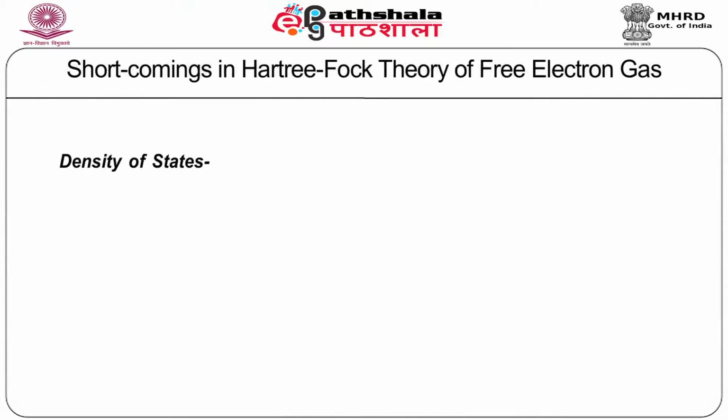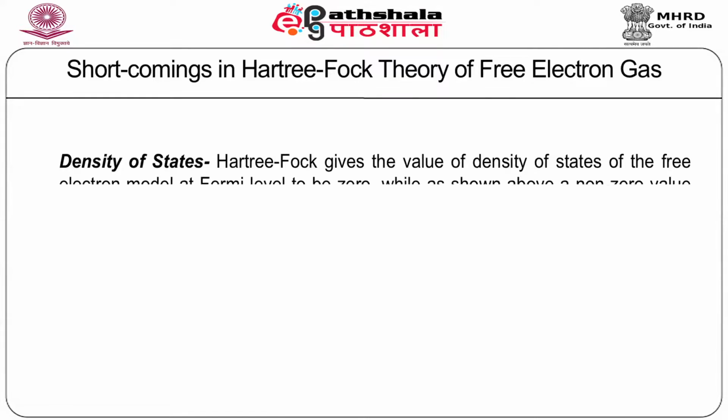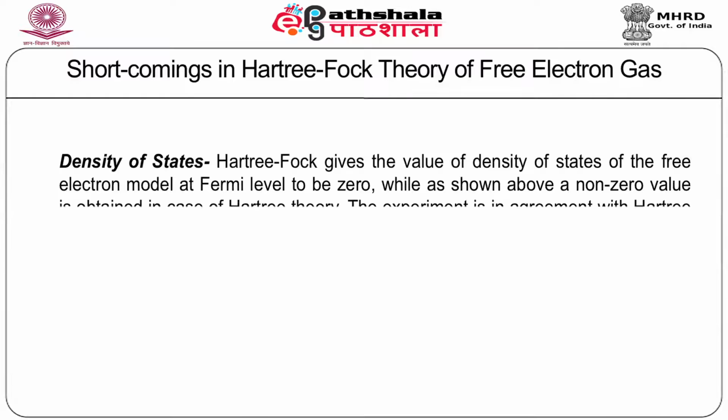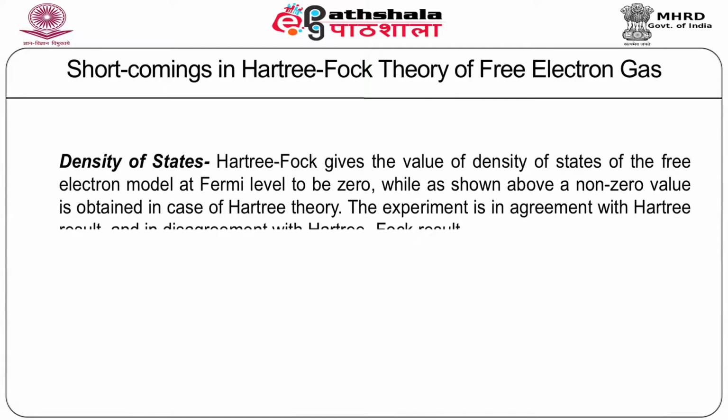The second issue is the density of states. Hartree-Fock gives the value of the density of states of the free electron model at the Fermi level to be 0, while as discussed before, a non-zero value is obtained in case of the Hartree theory. The experiment is in agreement with Hartree result and is in disagreement with the Hartree-Fock result.